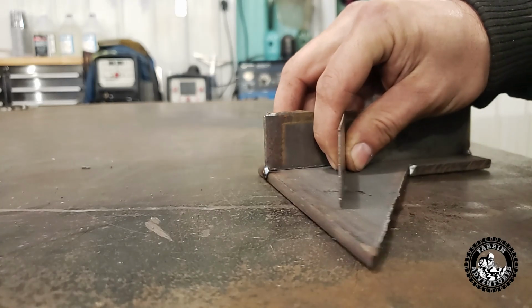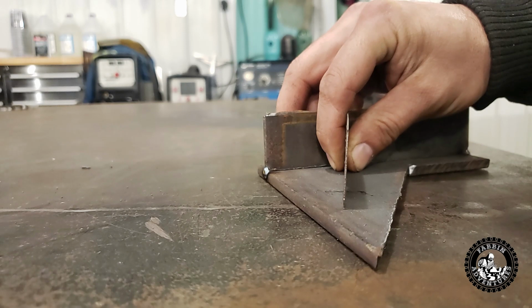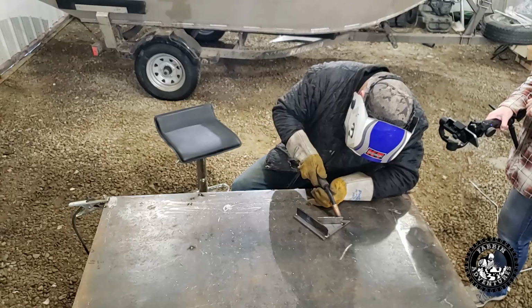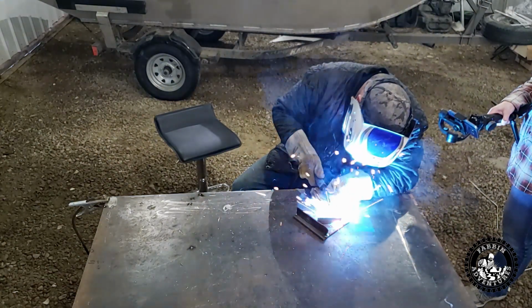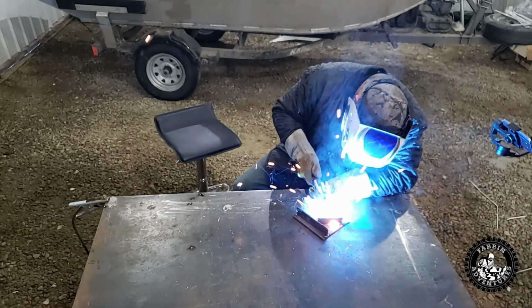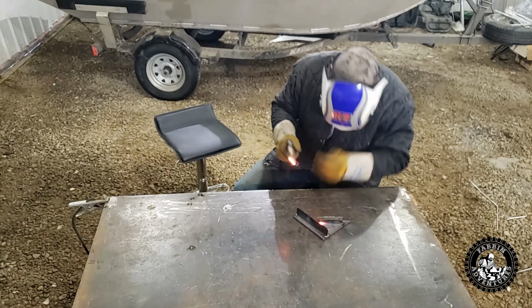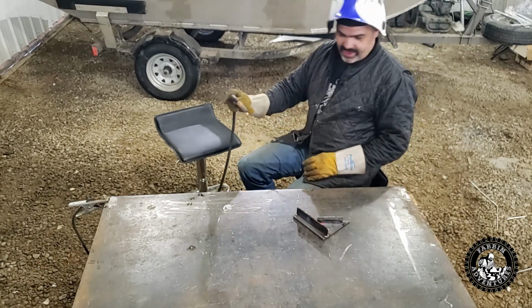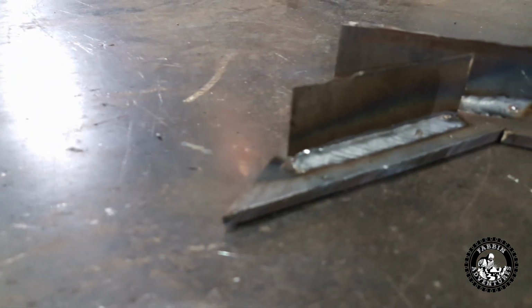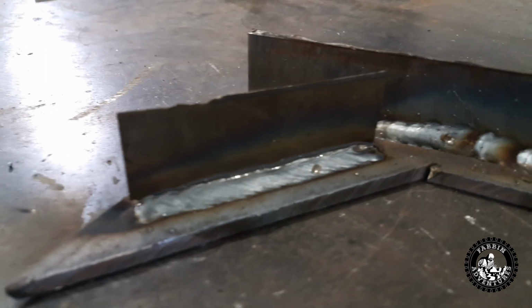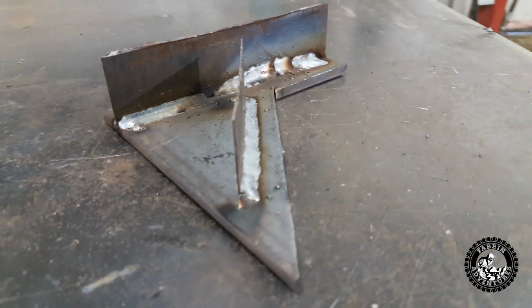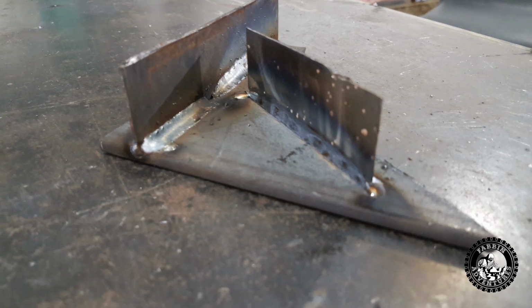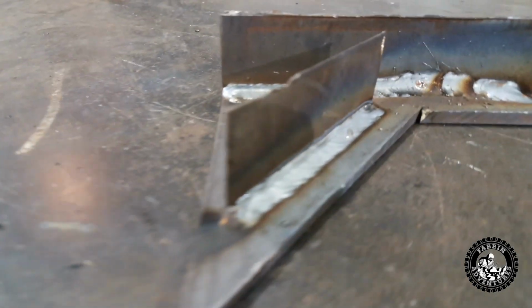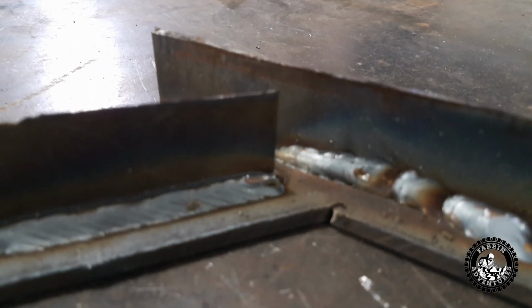I'm going to attempt to weld this 22 gauge thin sheet to a 1/4 inch plate, and we'll see if I can do it. That's a really tricky weld. And I pulled her off. I successfully welded 1/4 inch to 22 gauge without blowing through, except for right at the end. Right at the end there, I blew through a little bit.